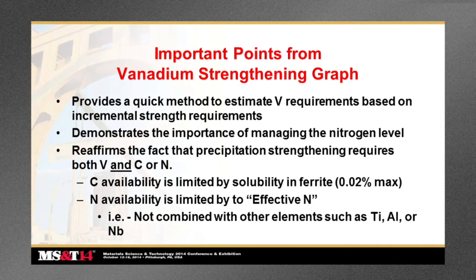Some important points from this vanadium strengthening graph: again, it provides a quick method to estimate vanadium requirements based on incremental strength that you are looking for. It demonstrates the importance of managing the nitrogen level. It reaffirms the fact that precipitation strengthening requires both vanadium and either carbon or nitrogen to be effective.